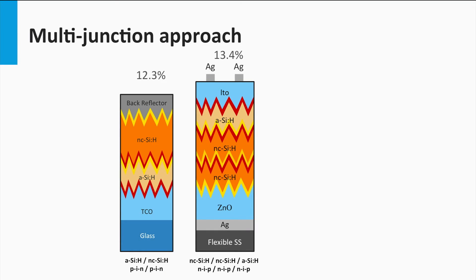Another aspect of thin film silicon solar cells is the current matching between the various solar cells. Textured surfaces are being used to scatter light into the various junctions to enhance the absorption path length, which allows to use thinner absorber layers. This becomes more important for the bottom cell, as this nanocrystalline silicon film is the thickest layer in the device and it has to absorb the most reddish part of the spectrum.